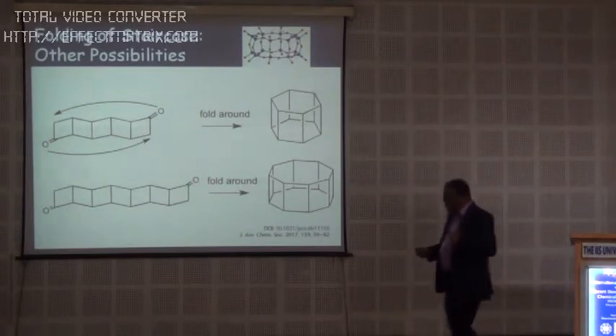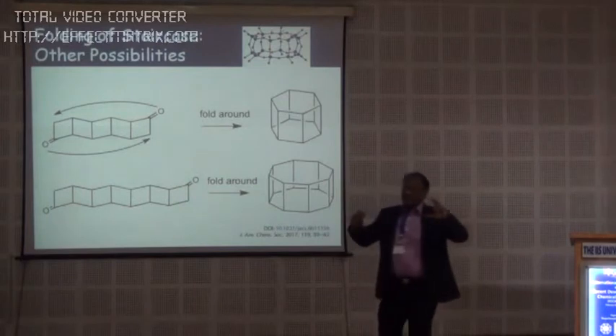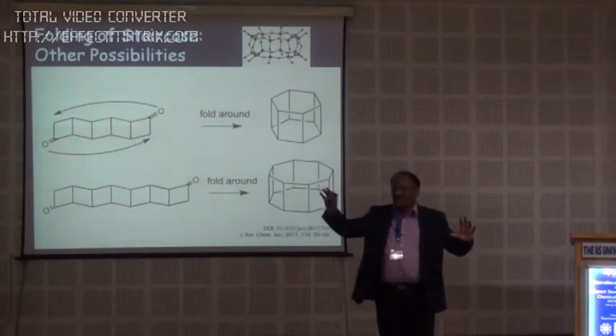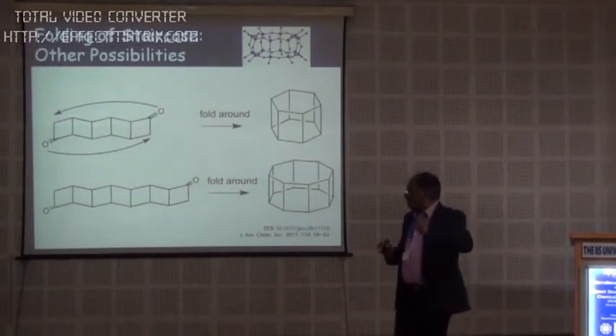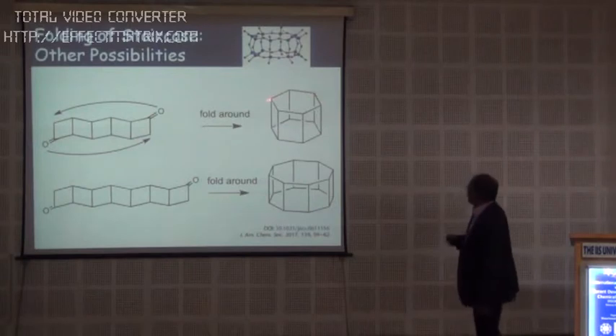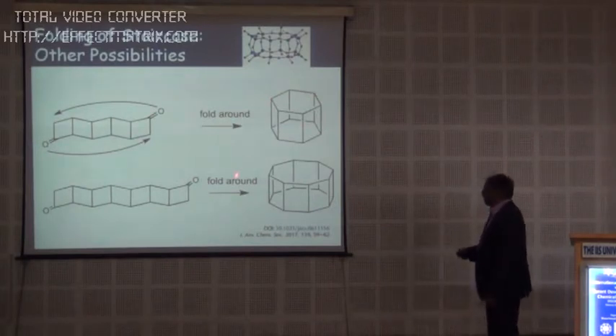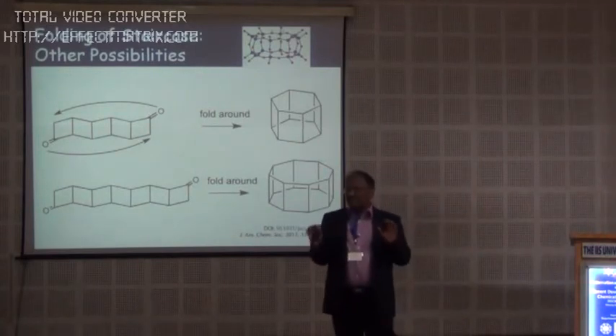So we went around looking for suitable templates to fold this around and make bigger drums. There's a reason to look for these bigger drums rather than the cubanes, because I showed that the cubanes can be connected at the 4 zinc atoms or at the 4 zinc atoms and the 4 phosphorus atoms. So you can have an eight connection there. Now if you translate that to here, you can have 6 plus 6, 12 connectors, and here 8 plus 8, 16 connectors. These are unheard of or unseen so far in the science. Their topologies have been worked out.